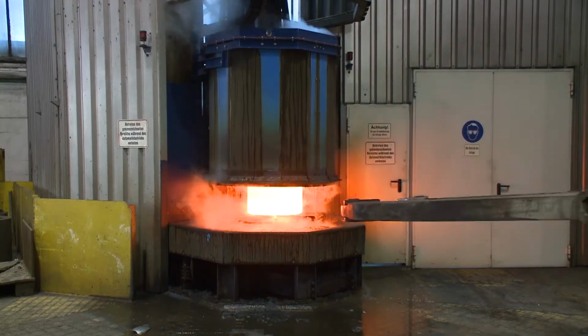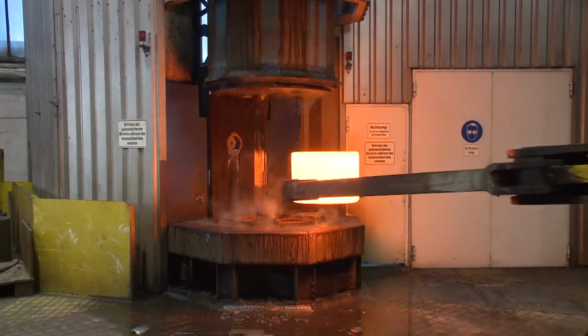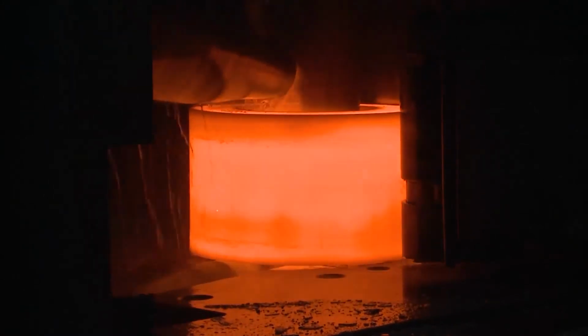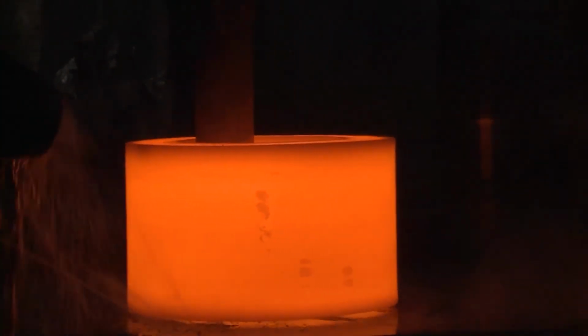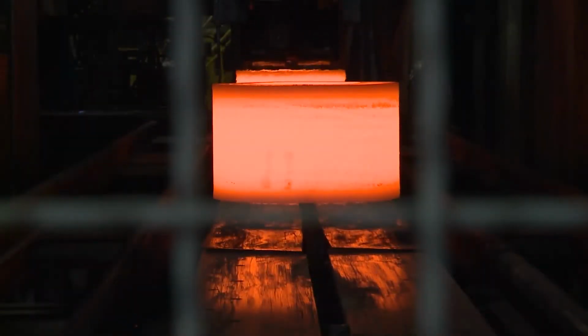After being cleaned of residues fully automatically, the heated blanks are rolled seamlessly with tight tolerances by minimizing the use of material and reducing efforts and costs. The rolling forces of the axial and radial stand go up to 250 tons each, so that rings with outer diameters up to 3,500 mm, thicknesses of up to 850 mm, wall thicknesses of up to 500 mm, and weights of up to 8 tons can be rolled.